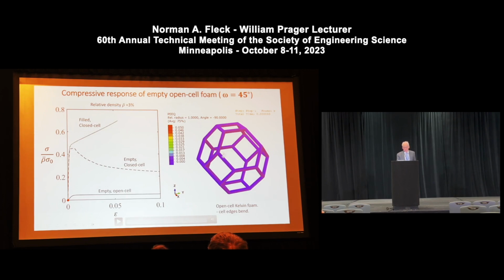So here's the Kelvin foam. It's a periodic unit cell calculation. I'm going to apply compressive displacements. I'm going to squash the cell and see how it performs. Here's the stress strain response in compression. I've normalized the compressive strength by the cell wall strength. I'm thinking of elastic, perfectly plastic struts here, and rho bar is the relative density. It's the volume fraction of material, typically a few percent.